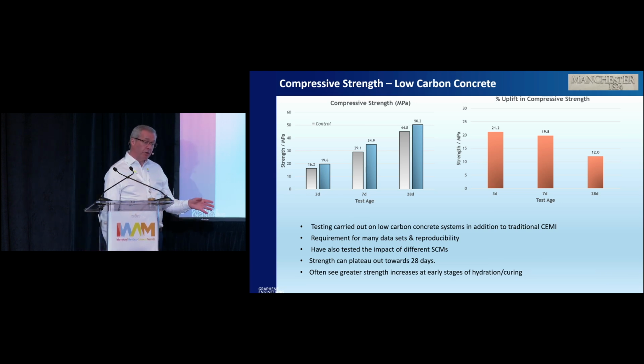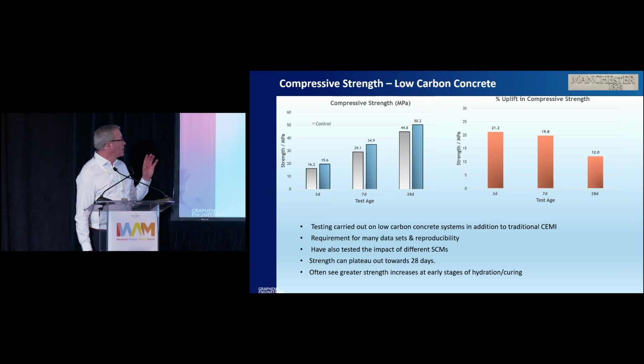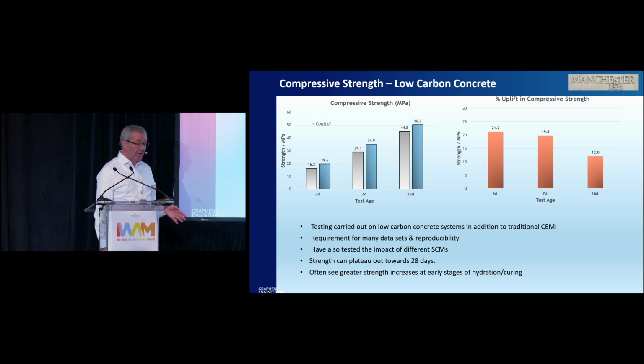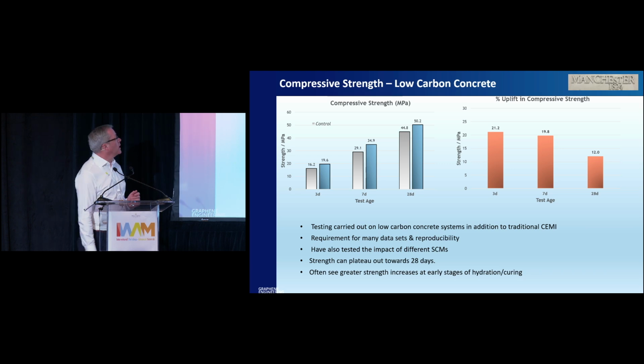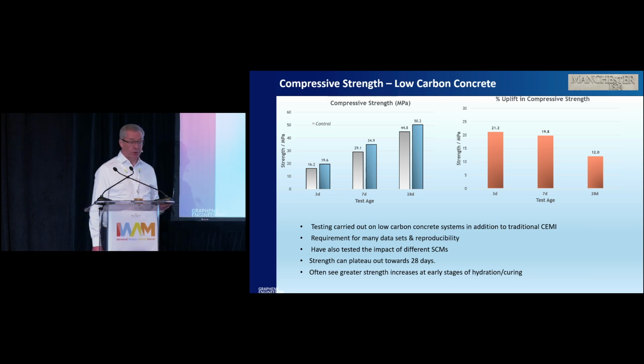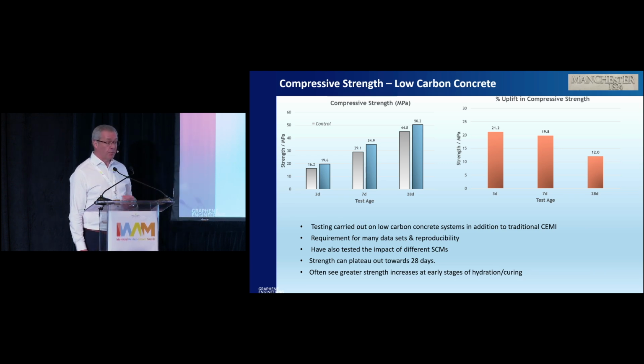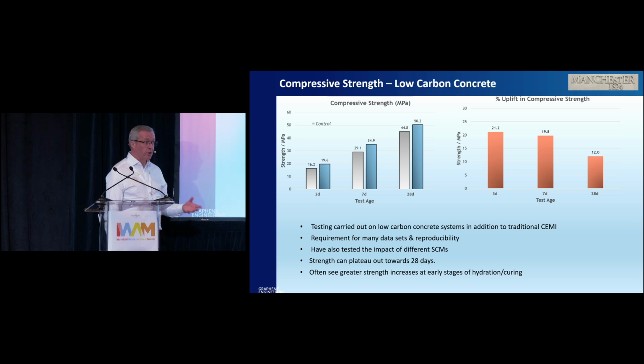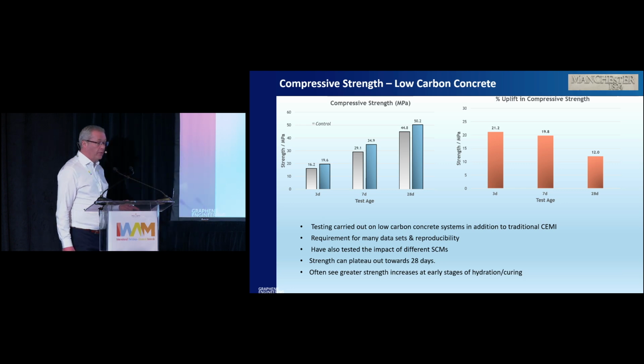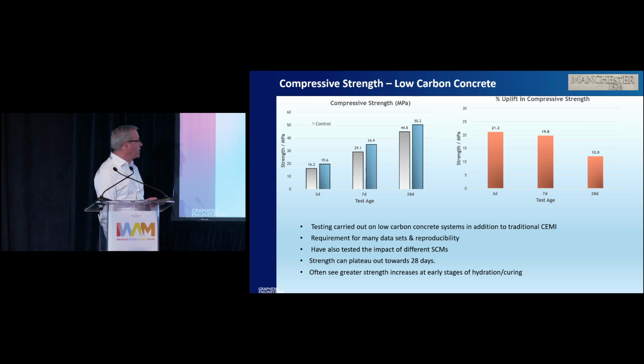In the laboratories, they've been getting consistent 30% uplifts, certainly on the 3-day and 7-day tests, and the papers have reported up to 40% improvements in compression strength and flexural strength. This is quite significant because you can take significant amounts of cement out of a system and lower your carbon footprint per tonnage of concrete. However, those trials in the field have undergone quite significant challenges.